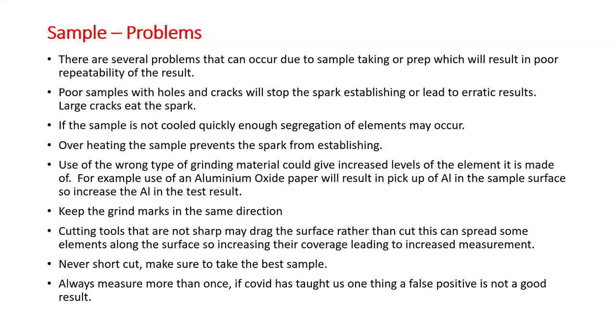I then decided to measure two or three times on the same spot. We could see the result was actually coming down as we were measuring it more times. The penny then dropped. I asked what papers they were using, or what substance their grinding disc was actually made from, and it was an aluminium oxide. So we changed the paper to a zirconium one. As if by magic, the aluminium disappeared and we got CP. So it was just simply pickup from grinding it with the wrong type of material.